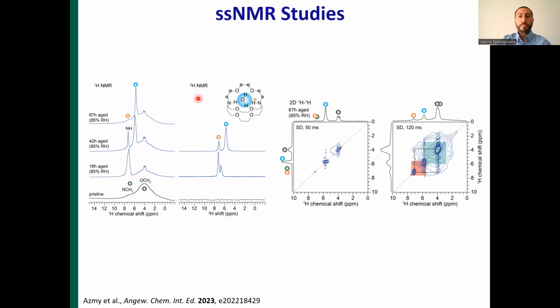However, we performed deuterium NMR studies where, of course, there is no deuterium on the pristine material, but with exposure at 85% relative humidity with time, we managed to record two signals which correspond to the deuterium atoms from the deuterium oxide molecules in the cavity, and also there was an exchange between the deuterium atoms and the protons of the ligand, which we also managed to record as this peak here from the deuterium atoms on the tertiary amine.